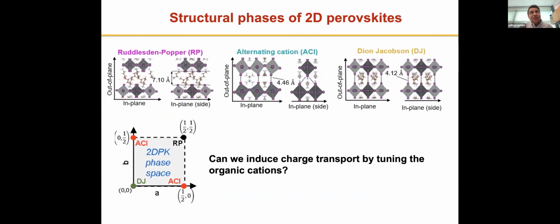Now, in addition to these Ruddlesden-Popper phases, which are shown on the left, you can also make other slightly different structural phases of these 2D perovskites. So on the right you can have the Dion-Jacobson phase. And you can see that the octahedra here sit right on top of each other, whereas in the alternating cation phase, they are offset in either the X or the Y direction. So if you plot the A and B directions of this plane, you can see that for the Dion-Jacobson phase,